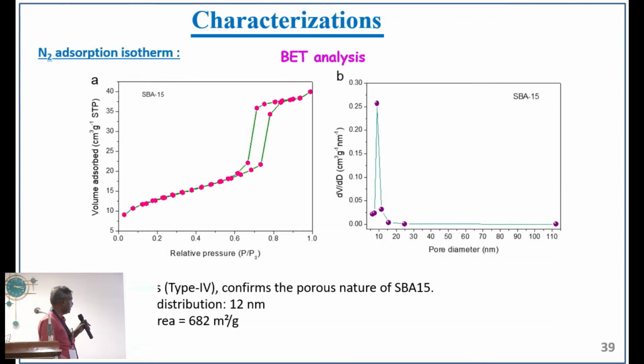So we characterized it using BET analysis, because the BET should be confirmed for the material. Its surface area should be around 700, here 682 m2/g. It is a type IV isotherm, which confirms the mesoporous nature, and the pore size is around 12 nanometers. The pore size distribution also gives very good uniformity, with a maximum of pores at 12 nanometer size. So the reproducible data is there.